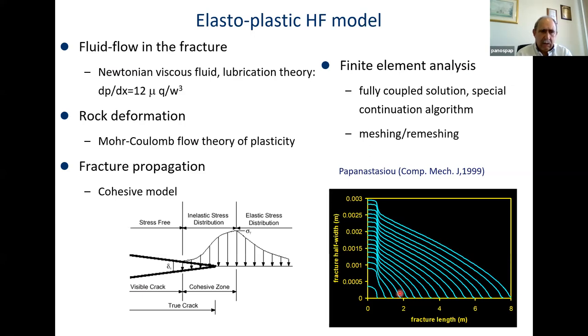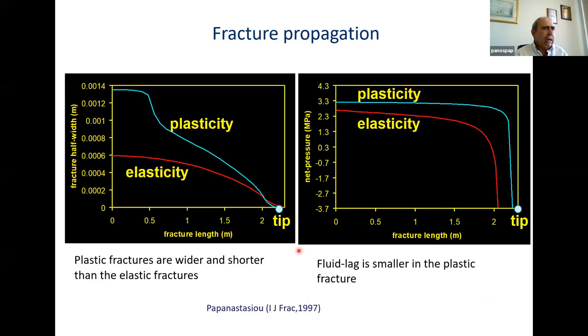This is an elastoplastic solution. The fracture profiles as the fracture propagates. And I will show some comparison. With plasticity, we get wider fracture compared to elasticity. And if I go to the pressure profile, with plasticity, the fluid front reaches closest to the tip, and we have all the pressure drop near the tip, as you can see here. And back at the wellbore, the pressures are quite close.